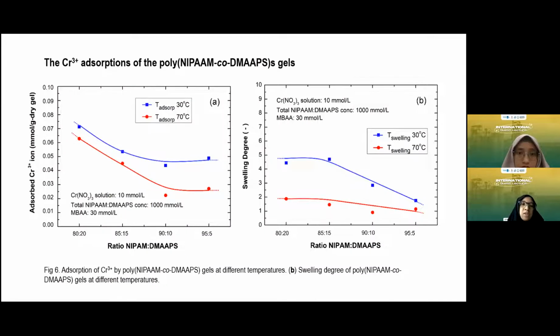Figure 6 shows the chrome adsorptions of the poly-NIPAAM copolymerized with DMAAPS gels at various temperatures and in various ratios between NIPAM and DMAAPS. As we can see, lower temperature results in higher adsorption ability of the ions. However, with increasing the temperature of the adsorptions, the adsorption amounts tend to decrease.